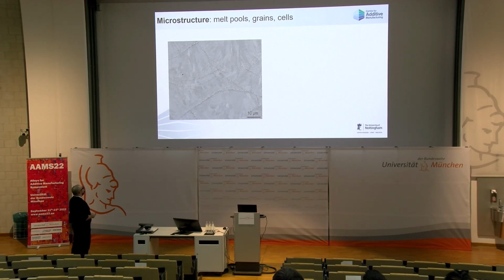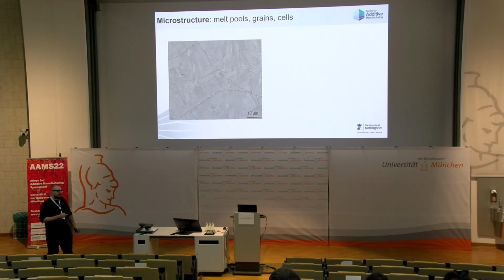Then we investigated the microstructure, because I wanted to have a look at this L-PBF microstructure. This is part of our still ongoing work. We still don't have EBSD data, but you can see that columnar grains can be found from the outside of the melt pool towards the core. So this is technically still a columnar microstructure. There may be a bit of refinement, but it's technically not grain refined.